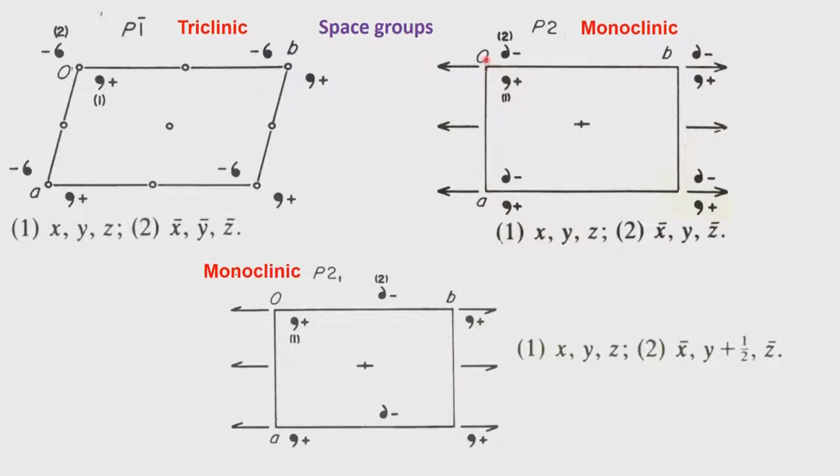You also notice that once we have this two-fold axis associated with the B direction, in the AC plane, particularly with respect to the A value which we have shown here in the projection, there will be an additional development of a two-fold axis at half position by definition. Any periodic repetition, as we have seen, will repeat its symmetry at half the distance, and this half the distance repetition will allow for the possibility of this point being related by a two-fold symmetry.